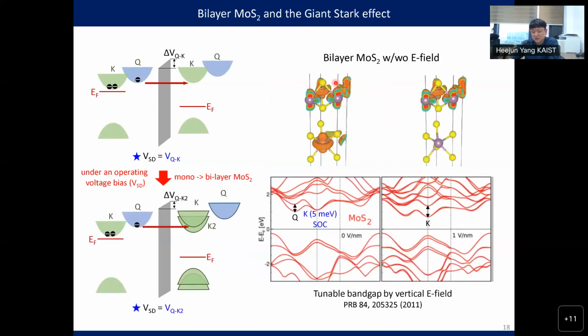So actually, it's similar to the quantum mechanical Stark effect. If we use bilayer MoS2 here and apply a certain electric field, imagine this bilayer MoS2, now instead of a single layer as in the previous case. The vertical electric field would accumulate electrons in one layer, and then we will have this degeneracy breaking. Even for K-valley electrons under an electric field, we have some charge displacement, and then we can break the degeneracy. This was discovered in the hydrogen atom, and it is called the Stark effect. So in 2D materials, we have a similar phenomenon, and then we have this degeneracy breaking.